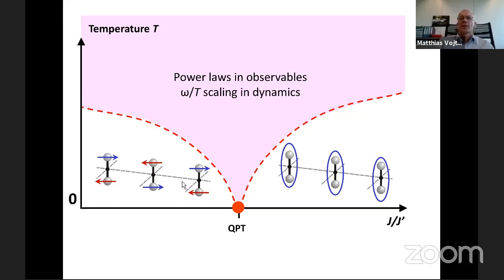If, of course, the frustration is strong, such that this ordered phase is suppressed, then this phase here may be replaced by a spin liquid, for instance. A game which we also played a few years back is you take 2 layers of a Kitaev model and play precisely this game. You have dimers on the right-hand side, and you have 2 weakly coupled Kitaev spin liquids on the left-hand side. Then you have a quantum phase transition between a paramagnetic phase, which is trivial, it consists of dimers, and a paramagnetic phase, which is topological, because it consists of 2 weakly coupled spin liquids. You still have a quantum critical point. The properties are now entirely different.